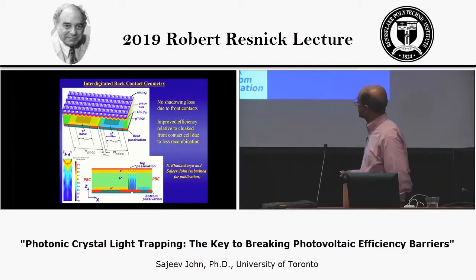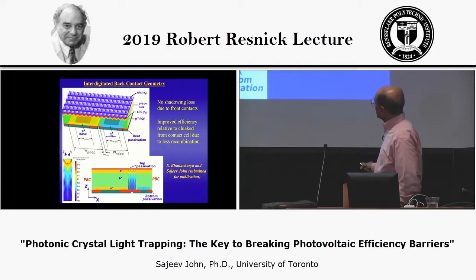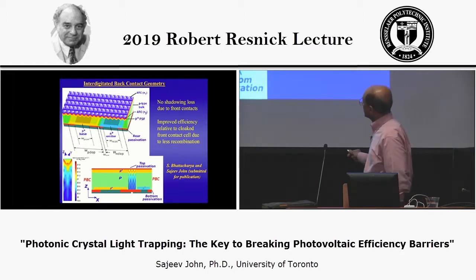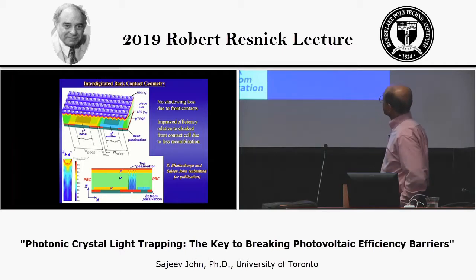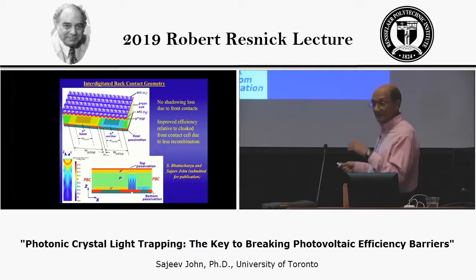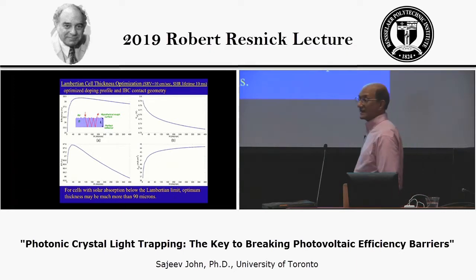So here's a side view of the same structure, P plus region at the top and one of the bottom contacts, and a high doping N region near the other contact. And this is the generation of carriers depicted here. This is on a much larger scale. This is about 40 microns and 10 microns here, whereas the lattice constant here is about, again, 2.5 microns. And as it turns out, this has an improved efficiency relative to the front contact cell that I discussed with you earlier. So what would the Lambertian cell do in this context of an interdigitated back contact geometry?